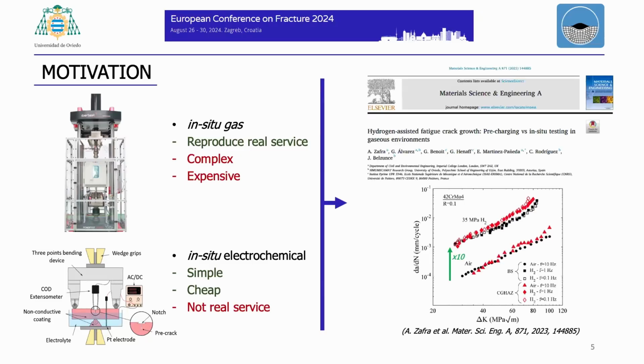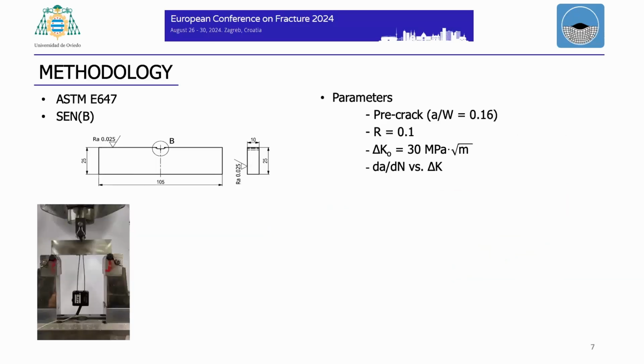In a previous study of our group, in collaboration with the Institute of Poitiers, we evaluated the crack growth rate of a chrome-molybdenum steel under in situ gas conditions. Here we have some of the results. So today, the goal of this work is to try to obtain this behavior that was obtained in gas condition, but with electrochemical methods. To do so, we follow this methodology.